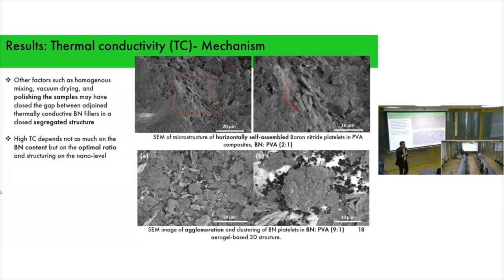So there are more SEM pictures of the microstructure of horizontally self-assembled BN platelets inside the PVA composite system. Apart from self-assembly, other factors such as homogeneous mixing, vacuum drying, and polishing the samples may have closed the gap between these fillers in the system.